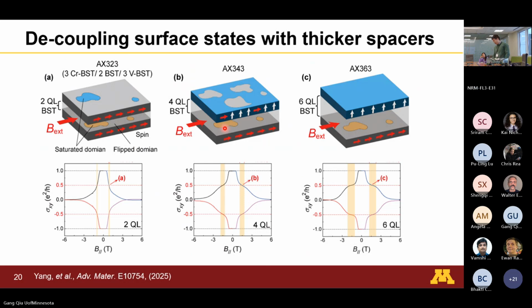All right, so this is not a full enough plateau yet. If you look at the data I just showed you here, you see it's a little bit wiggly, roughly at 1/2 of the quantization, right, but it's not fully developed yet. I said this is because the material quality is not good enough, but also because this is in very thin 2D films, right? You have 2 layers of magnets next to each other. They will couple, right? They will have some exchange interactions. So one example is if we increase the spacer layer thickness, you can see better and better developed plateaus in the shoulder here. Okay.